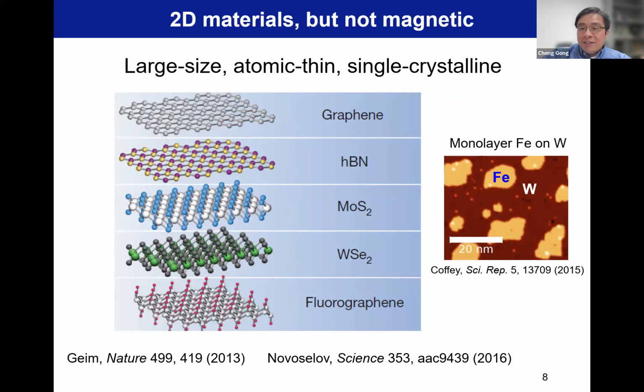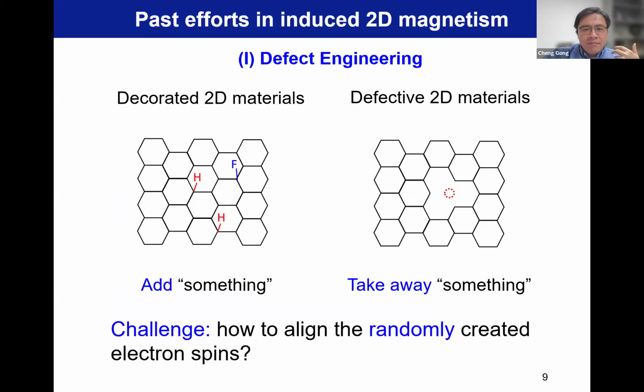Also, this MBE-grown magnetic thin film is strongly coupled with the substrate, so its properties are also altered. That's why in many different papers, you will see nominally the same materials show sometimes hundreds of degrees of Tc difference. So you can see if we can have magnetic order, ferromagnetism especially, in a layered material, you will certainly have different application prospects and even probably new physics.